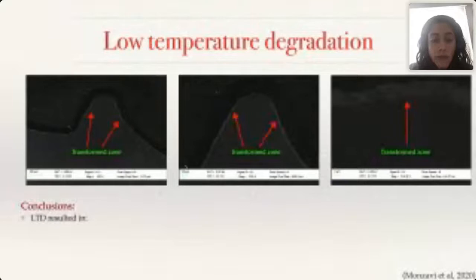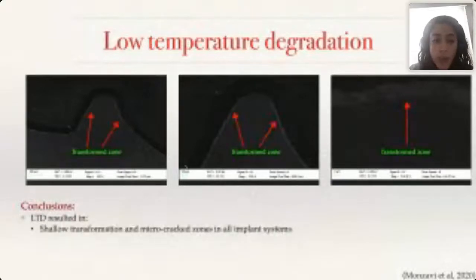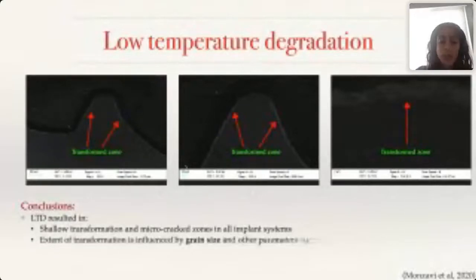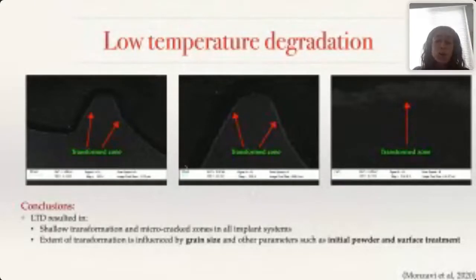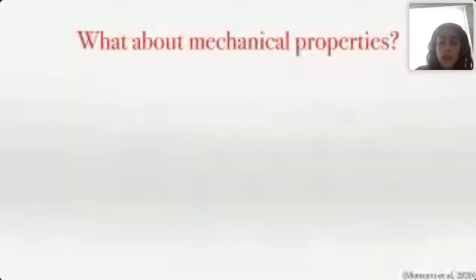So with the first part, we concluded that overall there was not much transformation and microcracking. They all had some transformation, but it wasn't really significant. What was important was that the extent was affected by the grain size and other manufacturing parameters, such as initial powder and surface treatment. But overall, we thought all the implants are safe to use clinically.